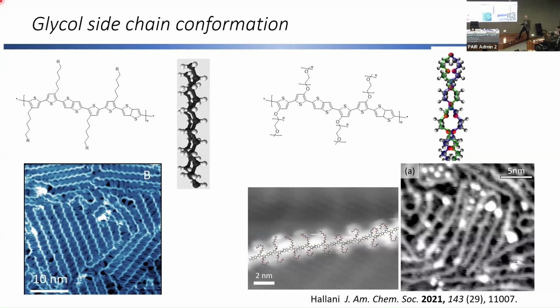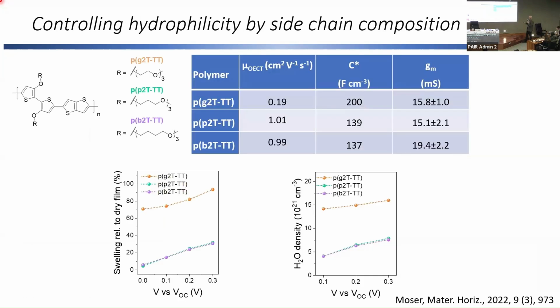So this is the problem with OECT materials, the lack of order due to glycolation. So we looked at a bunch of ways in which to minimize this, and one is to go from an ethylene glycol chain, where there's one oxygen for every 2 carbons, to one for every 3, and one for every 4. So we reduce the hydrophilicity, we reduce the swelling, and when you do this, your carrier mobilities increase.